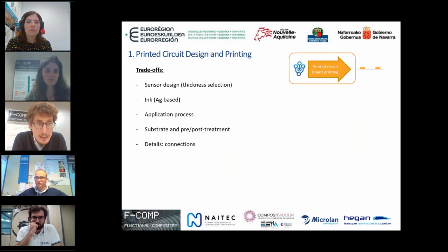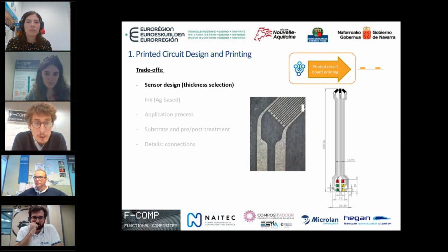In this case, we follow a series of trade-offs, starting with first the sensor design. In this case, as previously explained, we selected a strain gauge. We make the detailed design of the sensor itself plus the contact, and we started as well with iteration because the thickness of the tracks is related with the capacity of the process for manufacturing the track with the ink. So we make a trade-off between different thicknesses, reaching an approach where 70 microns of thickness of the track was selected. The image that we have in the middle, those small tracks, those are 70 microns.